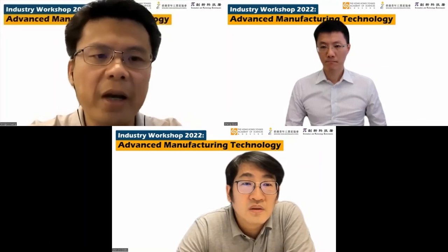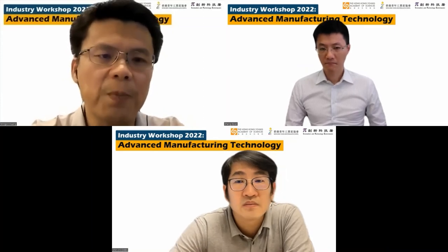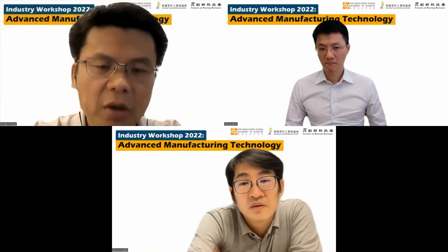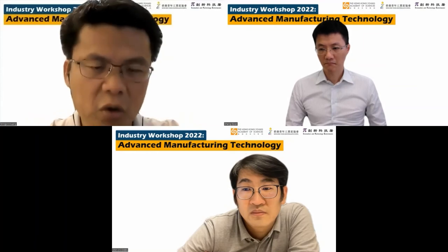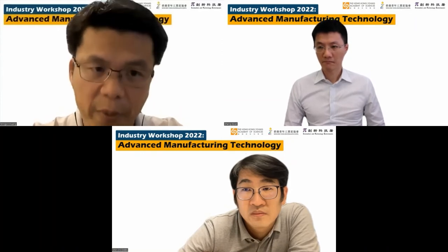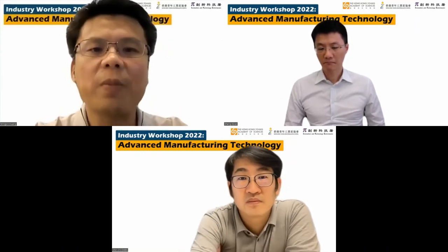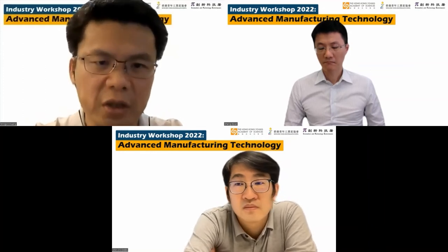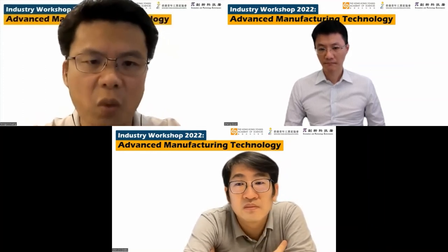Very clearly, we compare the tensile properties, the mechanical properties, the strength, which can reach about 500 megapascal, very similar to the normal stainless steel. The elongation reduced a little, but it's still sufficient for any application. We can still go beyond 30% of the tensile uniform elongation. So it's quite ductile, quite strong, behaving like a normal stainless steel. Of course, there is one drawback. The drawback is the reduced corrosion resistance compared to 316L.